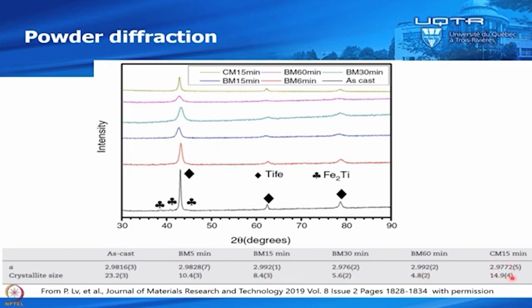And here for 15 minutes of cryo mill we have about 15 nanometers. This is bigger than this because this milling machine is not as energetic as the SPEX machine, the machine that we use for milling at room temperature. So that's why this crystallite size is bigger than this one, because they are made on different machines.